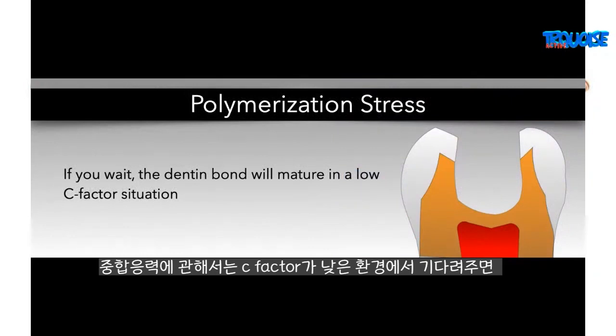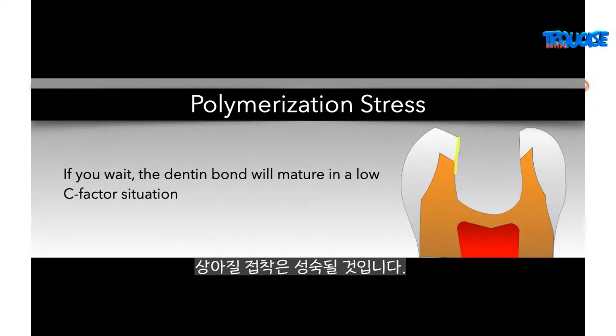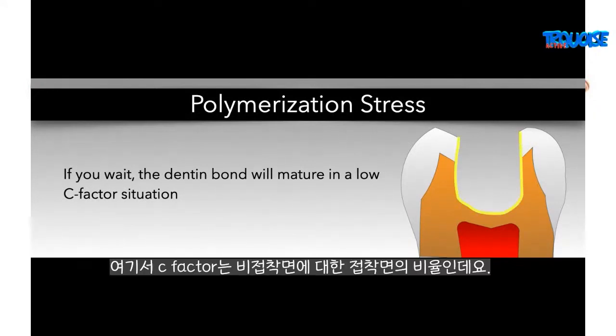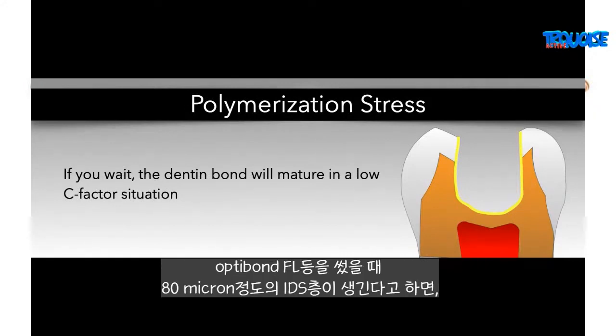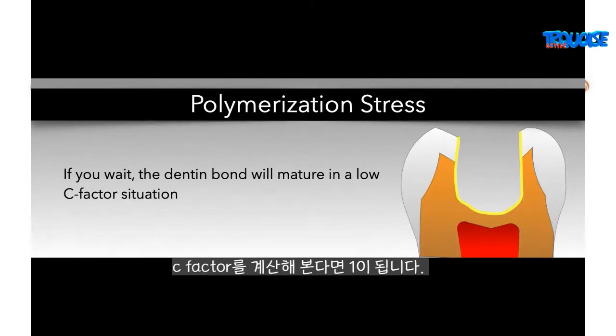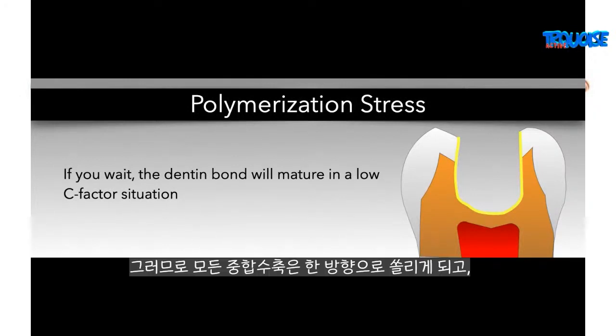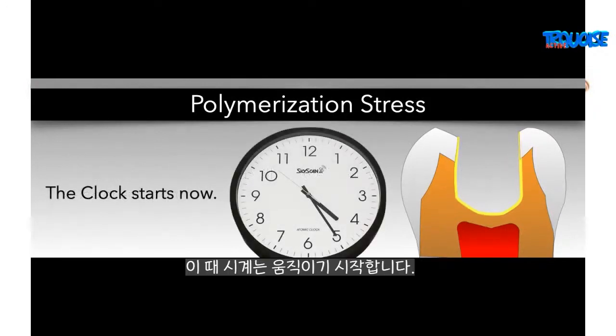So for polymerization stress, if you wait, the dentin bond will mature in a low C factor configuration. Here, the C factor is the ratio of bonded to unbonded surfaces. You can calculate the area of the bonded. If you have an immediate dentin sealing layer of 80 microns, like Optibond FL, then the ratio of the bonded to unbonded area is 1. It's the same. And so all of the polymerization shrinkage will go in one direction. And that's when the clock starts.